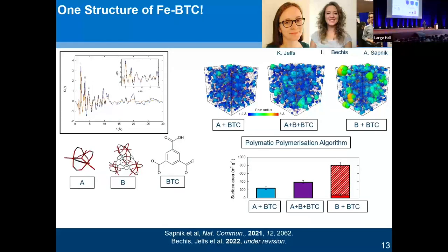The blue trace is our crystalline MIL-100, and the orange one up here is our FeBTC. Obviously, the FeBTC has no long-range order, so we see no peaks out at high r. But at short-range order, these two are very much similar. And Adam managed to predict the PDFs of what this trimer, the basic building block of MIL-100, would look like, what the supertetrahedra would look like. And of course, we know that it has BTC in.